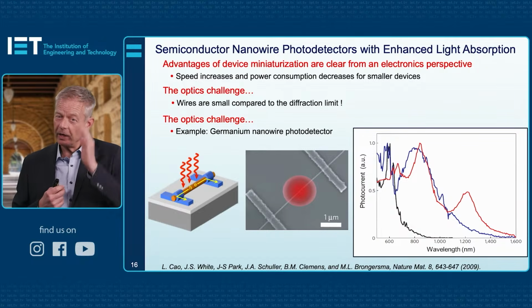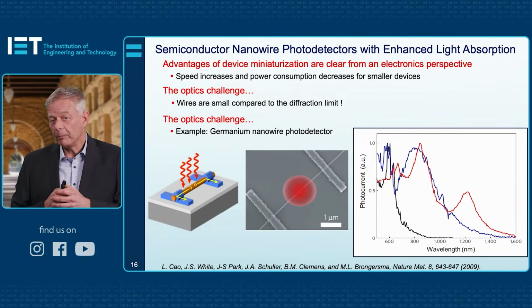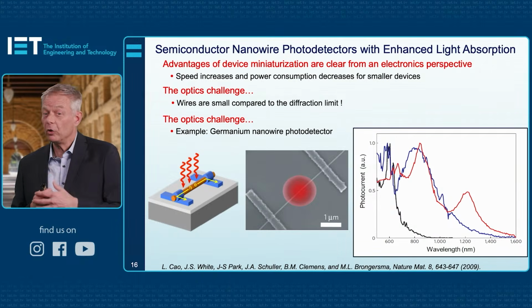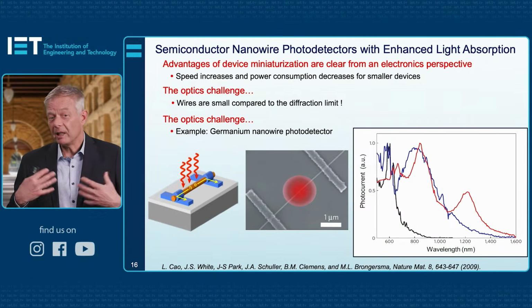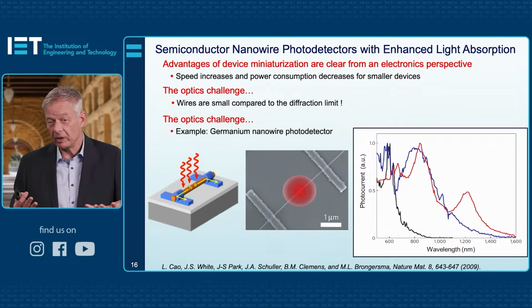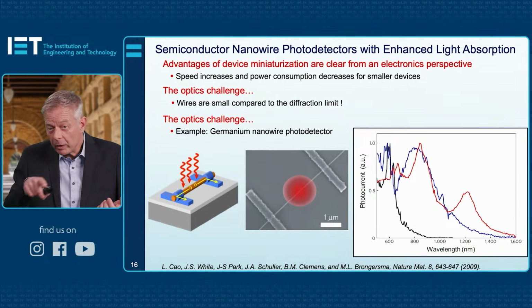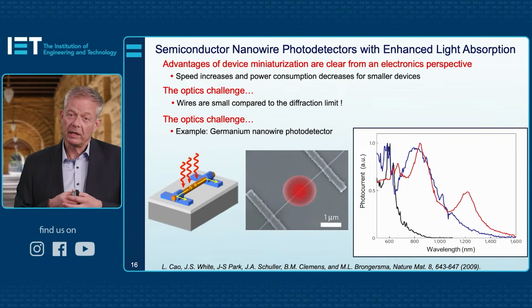Small wires resonate in the blue and green part of the spectrum, and bigger ones can show multiple resonances, where the light interaction or the absorption is enhanced by fitting the light wavelength once, twice, or three times around the circumference. Every time, due to the fact that the light circulates inside the absorbing medium, like in a solar cell medium, bigger photocurrents happen.